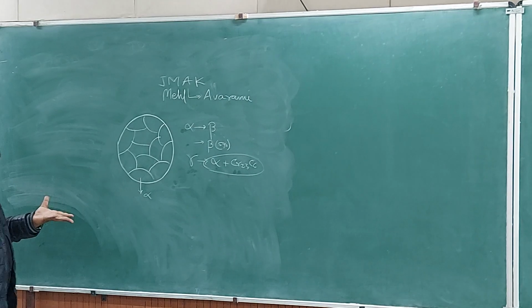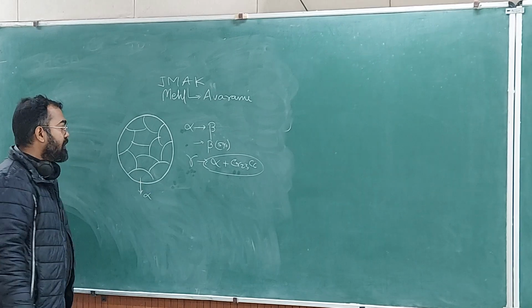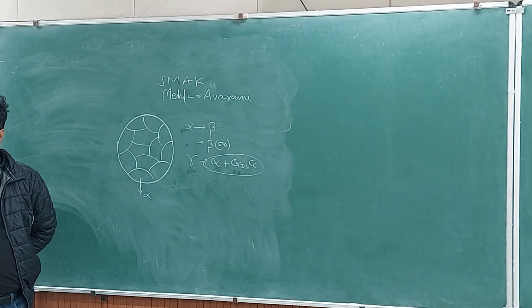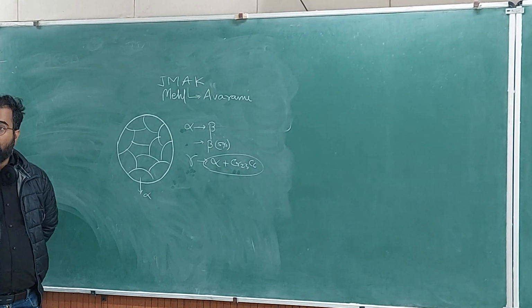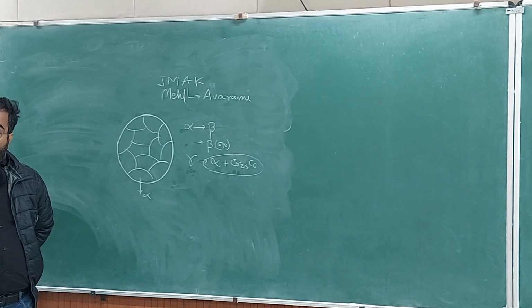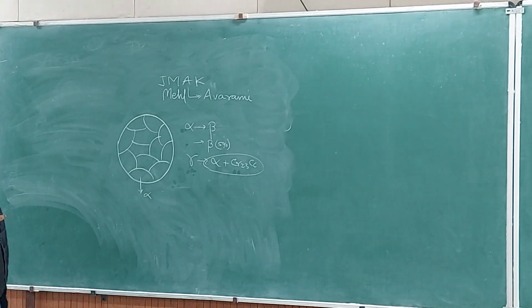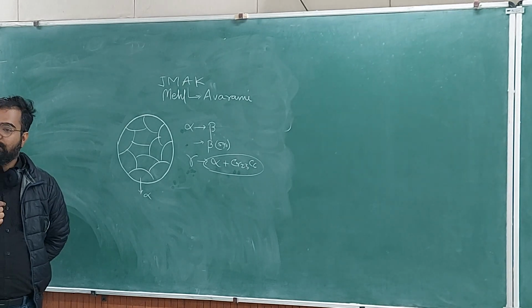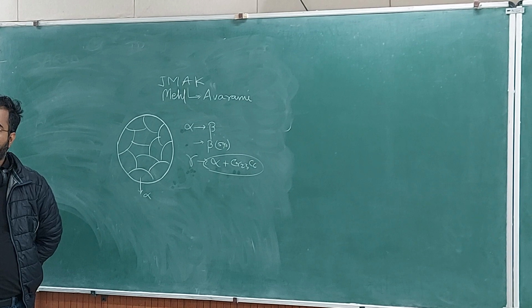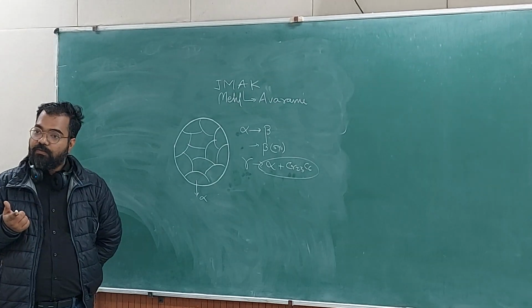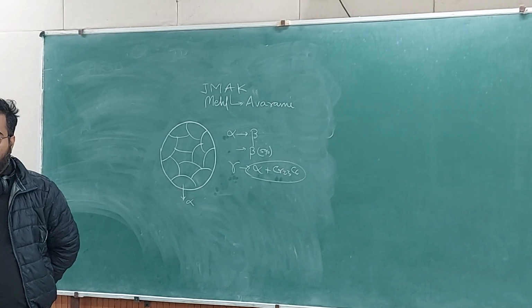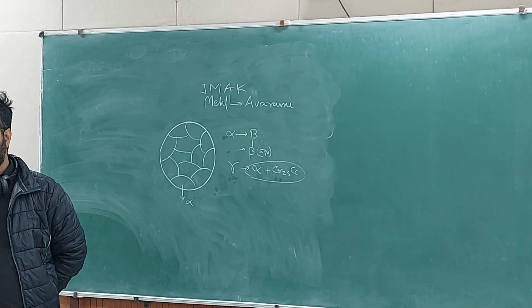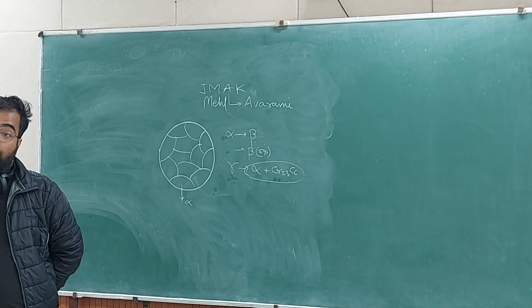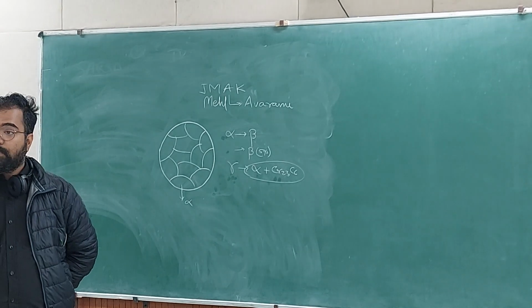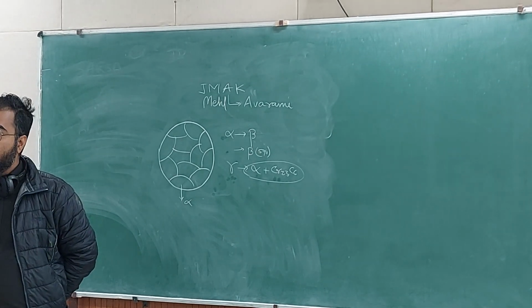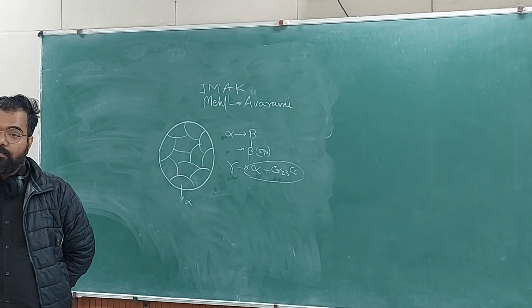So the second phase has to nucleate. And where will it nucleate? If beta has to start forming now, all the conditions are good, now beta has to form. Where will it form? Where is the surface? Grain boundaries. If grain boundaries are not there, suppose I have a single crystal, it's the same thing. Also in damage, it will initiate at the secondary phase interface, whatever is the weakest. If you have carbides, they will break. If it is ductile, then a void will form by breaking of the carbides or inclusions. If they are not there, then the grain boundary will nucleate a void.